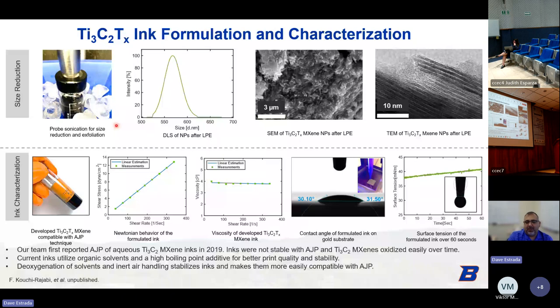And then after the sonication, we do DLS. You can see that we can reduce the particles down to around the 500 to 600 nanometer range in solution. And so that works well with the aerosol jet printer. These are just SEM and TEM images showing the reduced particle size morphology, but they do retain their nice layered structure. To make the ink, we can disperse these in different solvents.